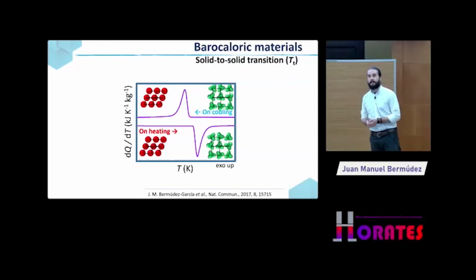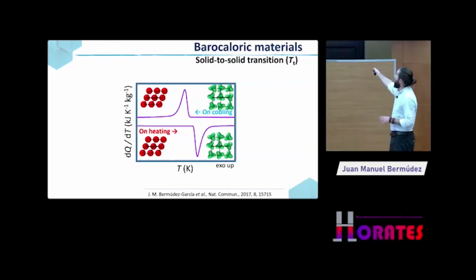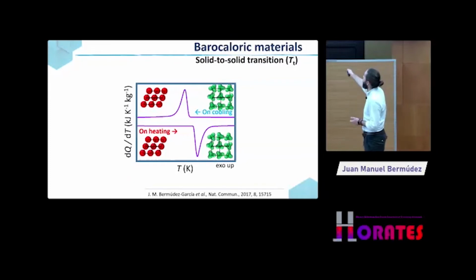So from this preliminary study, you can have some information like what is gonna be the maximum enthalpy and entropy change associated to the phase transition. And you can also know what is the transition temperature of your material under ambient pressure, as well as the thermal hysteresis. So you can obtain these three parameters from this basic characterization.